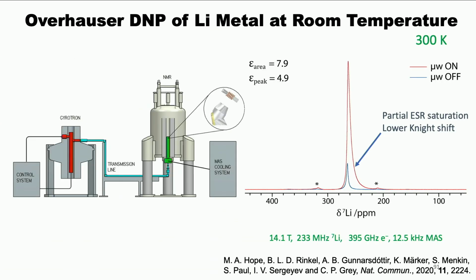But since then, we've upped our fields, and people like Bob Griffin in the chemistry department have worked a lot on this method called dynamic nuclear polarization, or DNP. And the challenge has been to find gyrotrons or mechanisms for irradiating the electrons at these much higher fields because of the difficulties of using microwave technology. And so here we are in 2020, and we've got an enhancement of 8. And it's not because we're particularly pathetic, it's because we just don't have the same high power as in low fields. But it's exciting, we can partially saturate it.